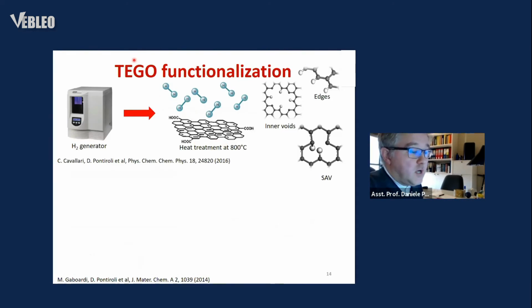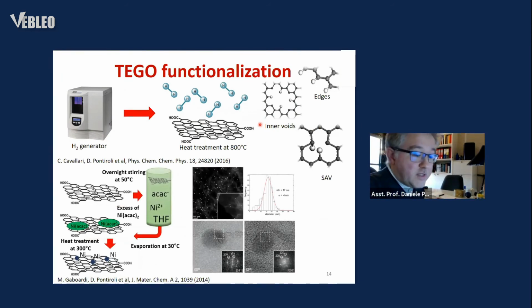TEGO can also undergo further functionalization steps, for example, high temperature hydrogen treatments. This process can lead to the partial saturation of the in-plane defects, such as edges and carbon vacancies produced during the exfoliation process. Alternatively, TEGO can be decorated with small metal or metal oxide nanoparticles, such as nickel, platinum, copper, or titanium oxide, for example. In this picture, we can see the synthesis route of nickel TEGO, in which nickel nanoparticles around 20 nanometers in diameter are grown on graphene sheets via the wet impregnation of a metal organic precursor, followed by the evaporation of the solvent and a heat treatment in vacuum.